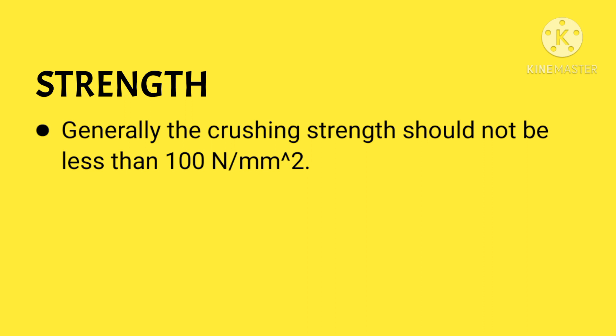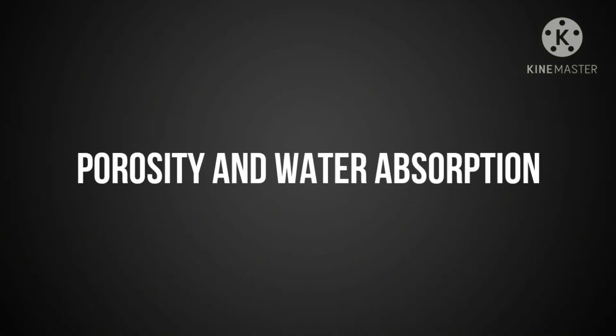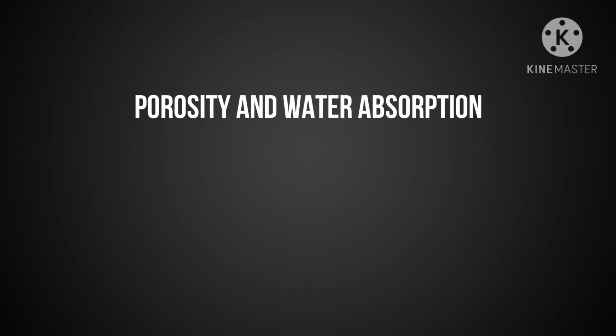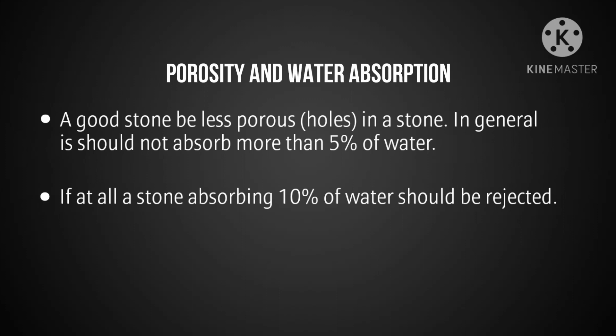Strength. Generally, the crushing strength should not be less than 100 newton per mm square. Igneous rock is stronger than sedimentary rock. Next, porosity and water absorption. A good stone should be less porous and it should not absorb more than 5% of water. If a stone absorbs 10% of water, then it should be rejected.